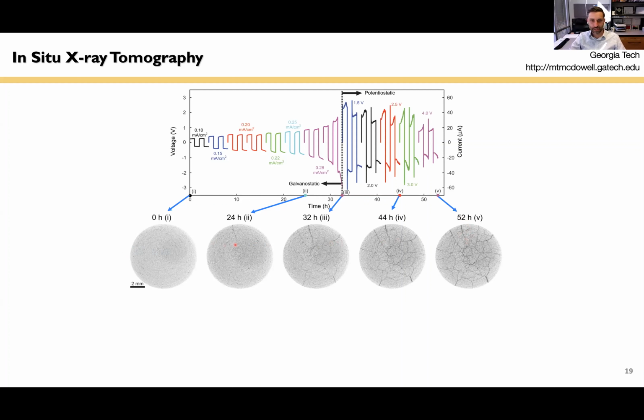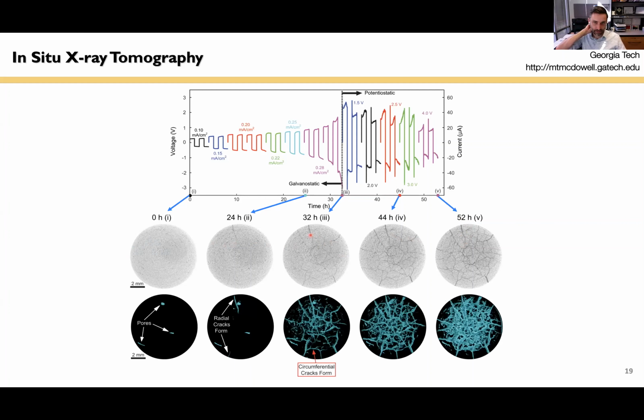I think the most distinct thing that you can see here is that there's these dark lines that grow in as we cycle this. And in fact, these lines are cracks. So we are cracking and fracturing this solid electrolyte pellet into a bunch of pieces, actually. And you can see in this bottom set of images, this is the 3D fracture pattern that we've segmented out from this data. So it's almost a spider web-like pattern of cracks. This is different than the data I just showed you. In the synchrotron data with the sulfide solid electrolyte, I showed you that we lost contact at the interface, and that caused failure of the cell. Here, the cell is a little bit different. This is done in a coin cell, and contact loss is less of a problem.